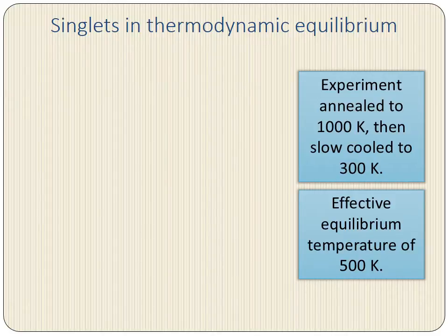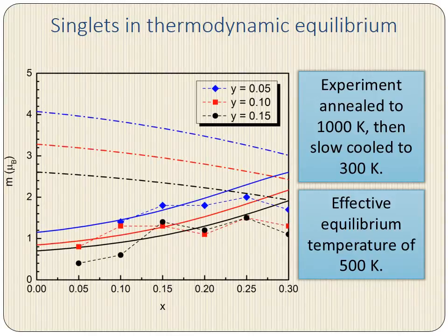With this chosen, how do things compare? Quite well, especially considering that this temperature T is the only tunable parameter in our model. Two things to note here. First, the overall reduction is of the same magnitude as experiment. And even more importantly, the trend with hole doping now moves in the correct direction. Therefore, the moment reduction observed is due to singlet formation in some sort of thermodynamic equilibrium.